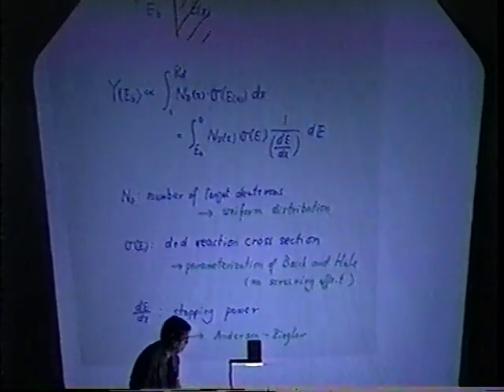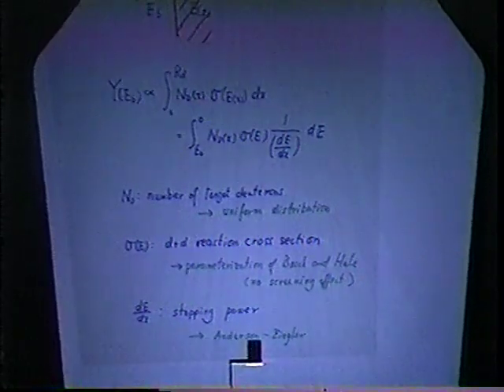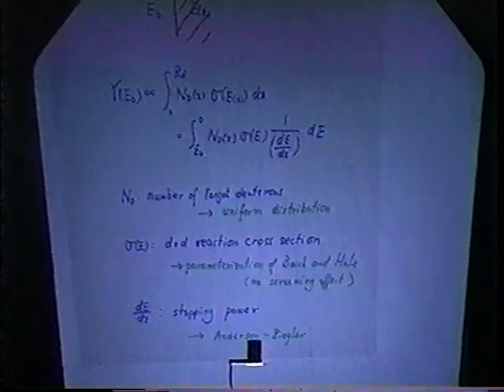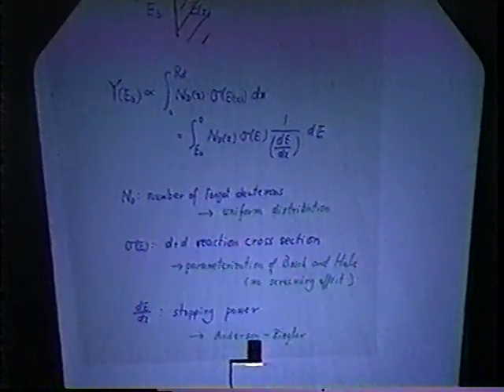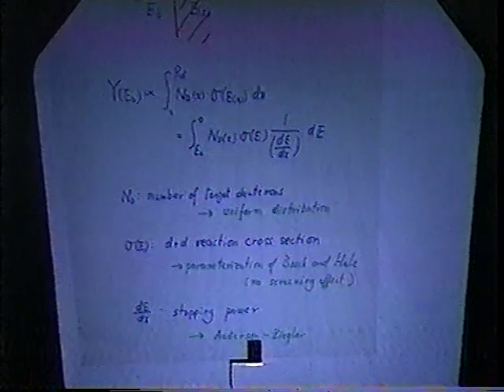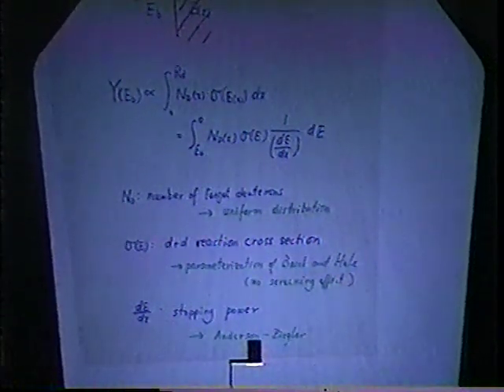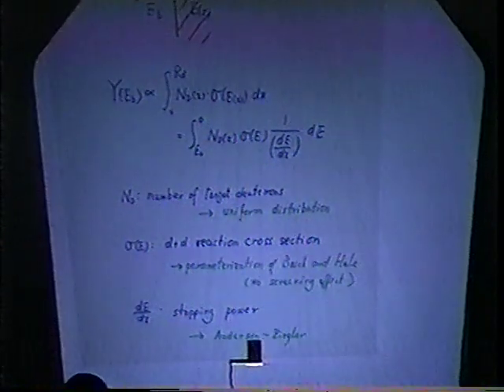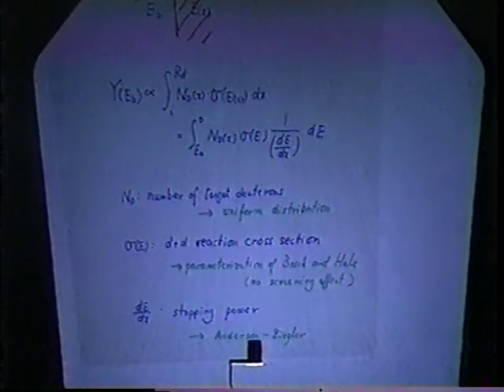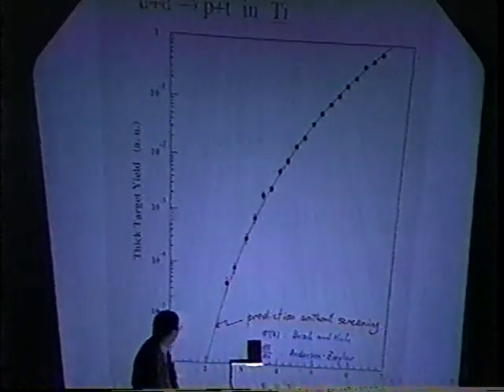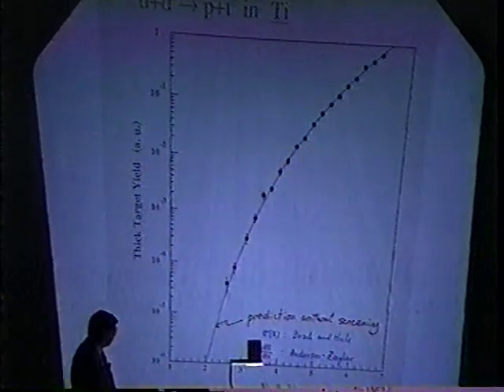So for these, I just assume the ND is a uniform distribution, and sigma cross section is from a parameterization of Bosch and Hale. In this parameterization, we cannot expect a screening effect because these are parameterized at rather high energies. And also for the stopping power, we took the Andersen-Ziegler's value. So the experimental data shown was divided by this predicted value, and we plot like this.